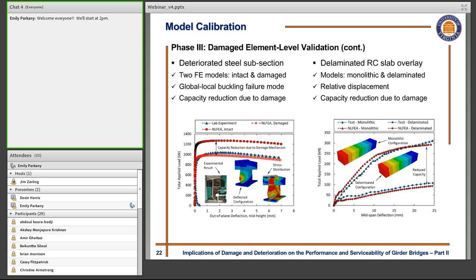And if you compare the results from the intact model and the damaged model, you can see the level of reduction in the capacity in this specific specimen because of the existence of this type of damage. In the other case, the overlaid reinforced concrete slab, we had two models: the intact configuration, where we had the full bond between these two layers of concrete, and also the delaminated case, where we used the contact elements to make the separation between these two layers. As you can see, the numerical models were in good agreement with the experimental data, and again, comparing the results from the intact model and damaged model, you can see the amount of reduction in the capacity as a result of the existing damage configuration.